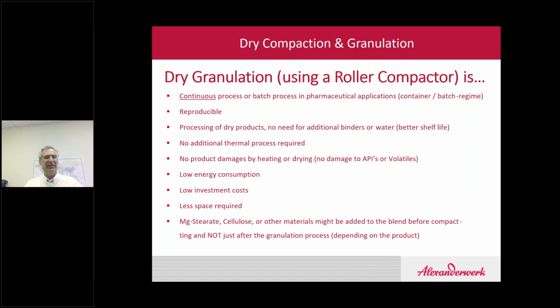So if you have very heat-sensitive APIs or volatiles in there, there is no thermal concern about the material being processed. A lot of customers ask, what kind of a delta T do I see across the system as I'm running a roller compaction process? And typically it's limited to about 3, 5, 10 degrees Celsius, maybe from beginning to end. It's a very low energy consumption, obviously, since we're not putting a lot of heat into the product. We don't need to spend a lot of energy to do this operation.